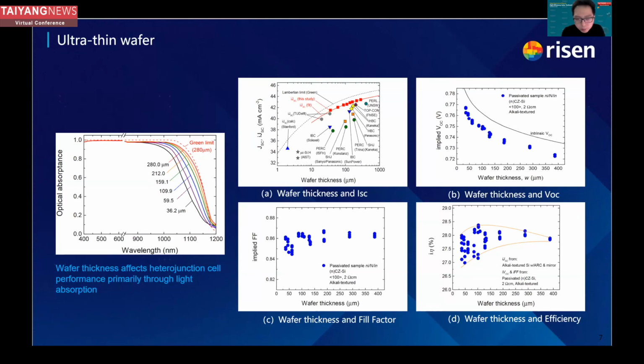With wafer thickness reduction, we're seeing that the efficiency and fill factor increase a little bit first and decrease slightly when reaching 100 micrometer. And by the observations and studies, we found that by slightly decreasing from 130 to 100 micrometer wafer, the efficiency and fill factor will have no big change. So we believe that efficiency will not be compromised when we're thinning the wafer to 100 micrometer or even slightly lower.